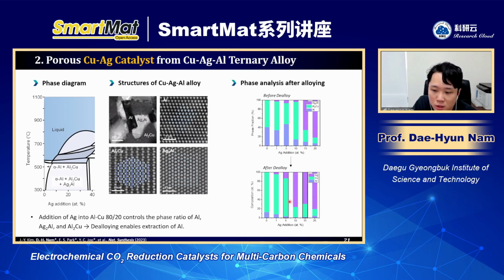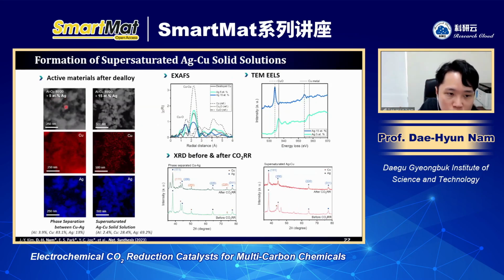So in this way, we found that with 5% and 15% silver, the interface can be changed. For example, in the case of 5% silver, after we do the dealloying, when you look at the copper and silver, we found they formed a phase-separated copper silver interface. This is the general interface, which we can predict from the miscibility of copper and silver. Interestingly, when we mixed 15% silver content into this alloy, we could fabricate a supersaturated silver copper solid solution. It means that some copper is mixed into the silver and some parts are separated. So these are quasi-mixed states. This is different from this totally separated one.